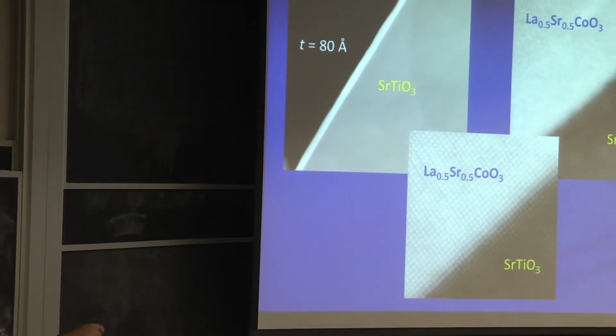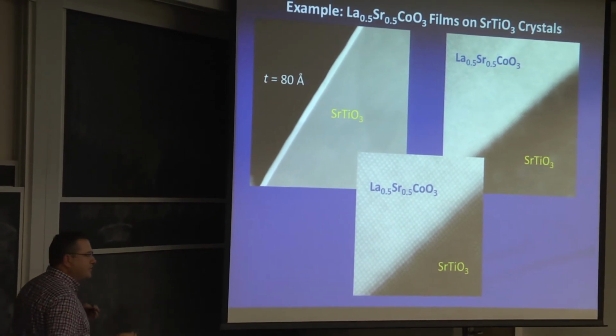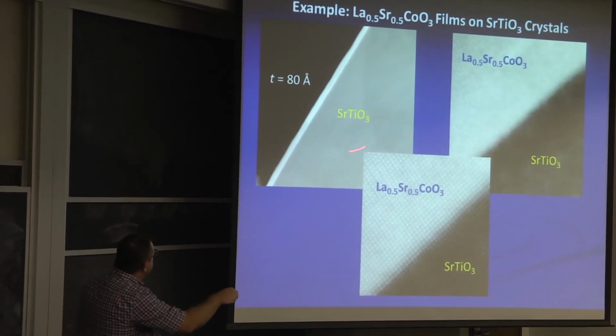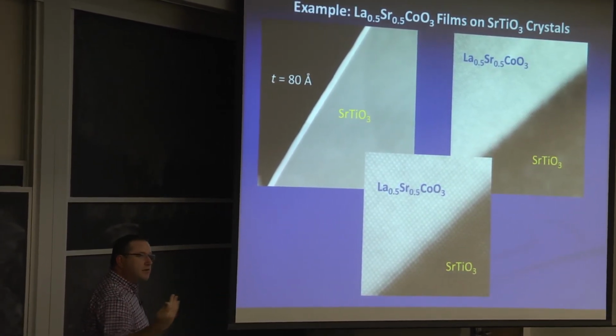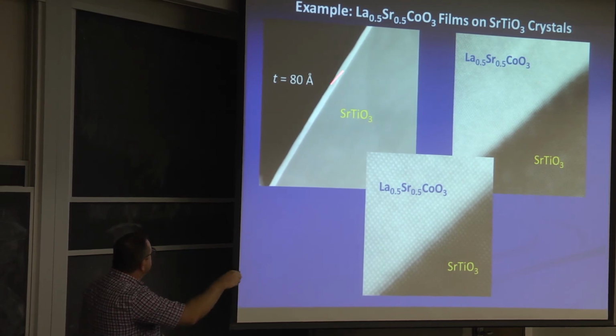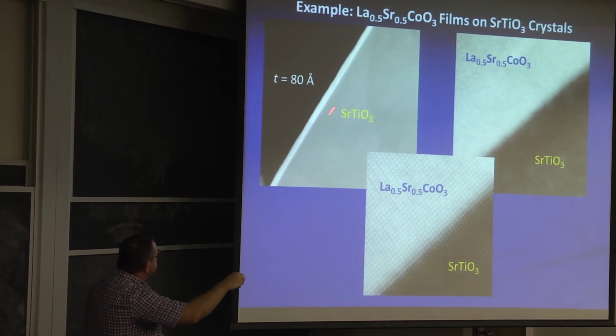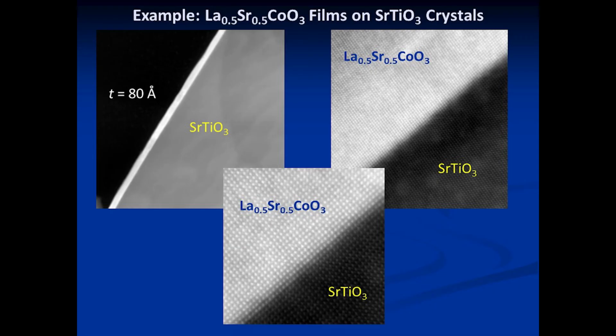So this is a picture. Lanthanum strontium cobaltite, one of my favorite magnetic materials. It's grown on top of a big slab of strontium titanate. You're looking at it from the side. This is just vacuum. This is the film, and this is the interface with the substrate, and this just shows it getting to higher and higher magnification. The magnification here is a little bit over 1 million times, and this is the interface, and you look at this thing and you think, wow, this is just fantastic. It's exactly what I drew. Literally cubic perovskite growing on top of cubic perovskite. I don't see any defects anyway in the structure. This looks just fantastic.